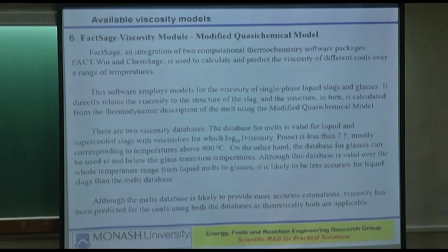We grind it out and then measure its viscosity, because they are the calibration standards. They are very well characterized with respect to temperature and viscosity. So, just like any other experimental measurements, you need to calibrate against the NIST glass.